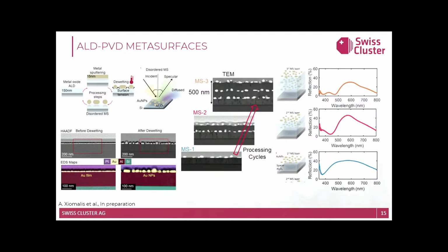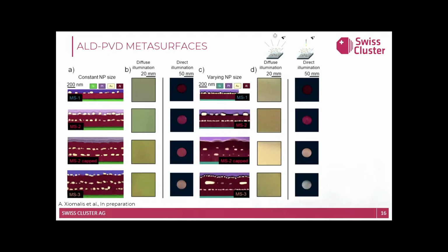So you can see that going from one layer to 2 layers to 3 layers, we measure the optical response of these types of structures, going from a broad spectrum for 1 layer to a much narrower spectrum for 3 layers, and also reducing the reflection. So we can do this for having different numbers of layers in which we maintain the constant nanoparticle size. And then we observe the diffuse illumination and the direct illumination so that we can tailor this optical performance. And we can do this also by varying the nanoparticle size in different layers. So we can do this all in the same system in just a one-step approach.